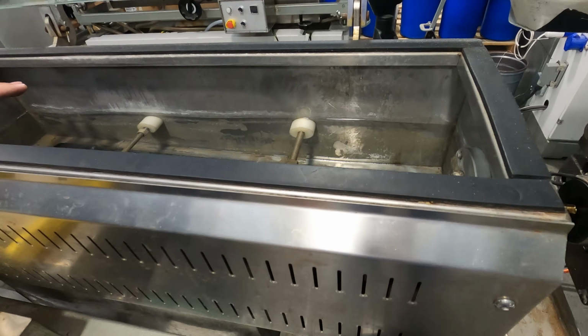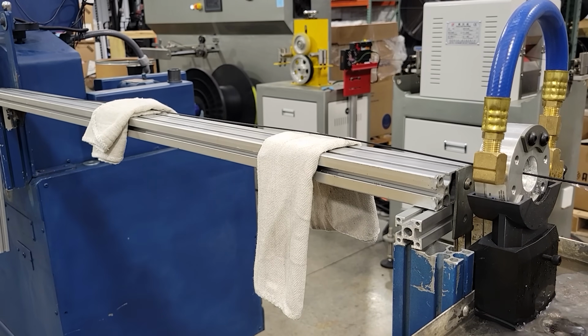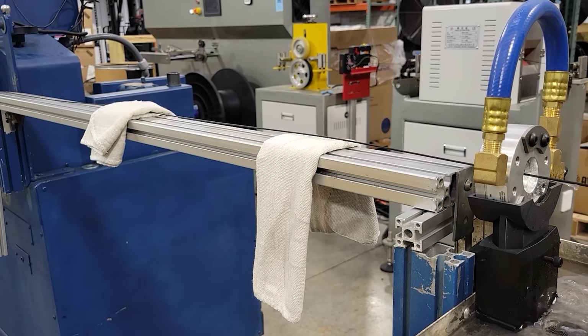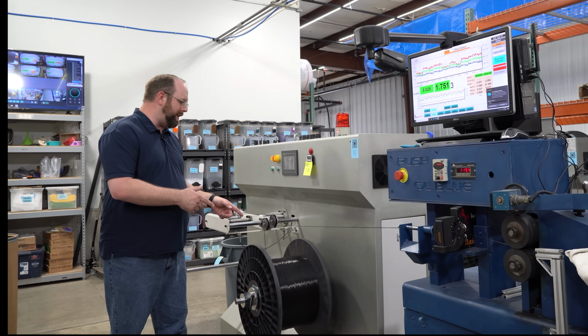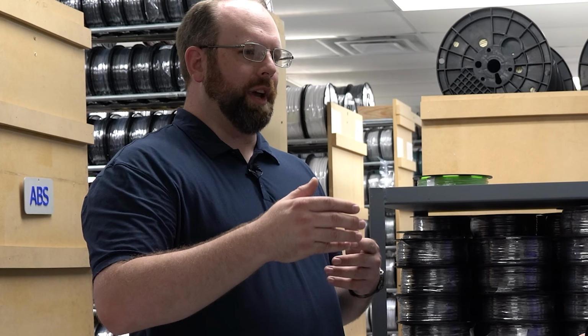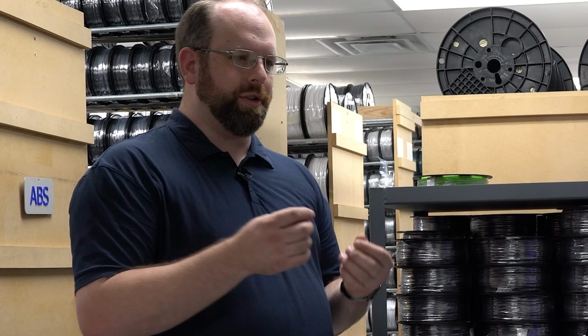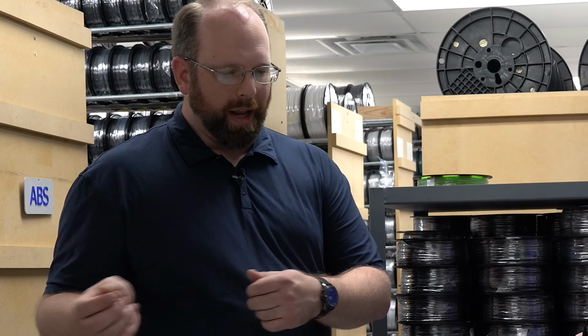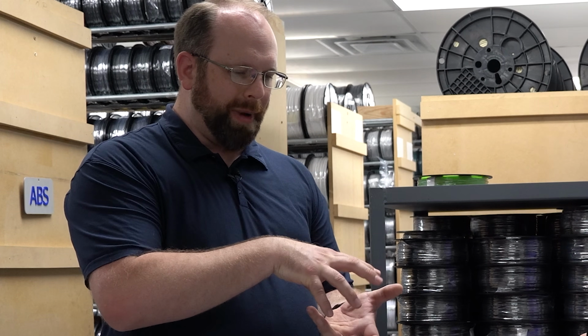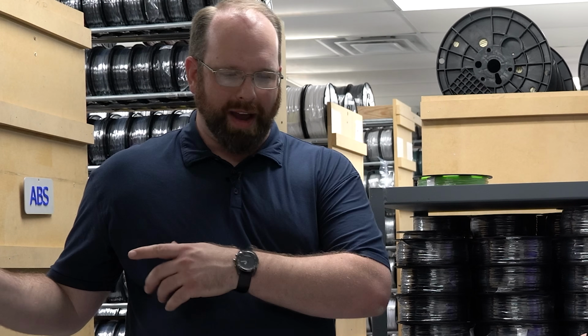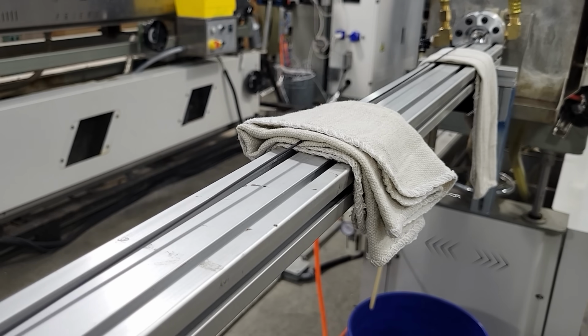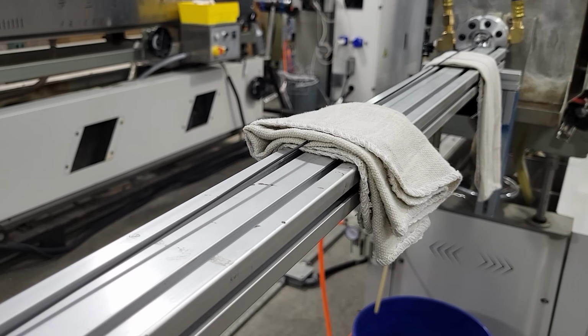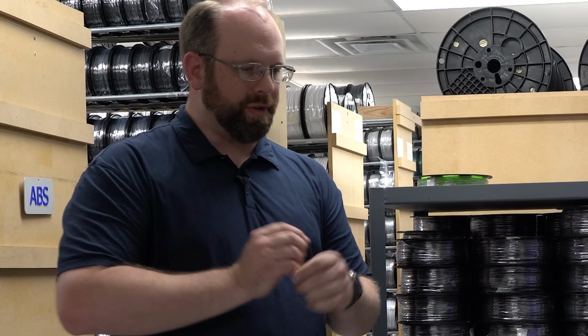I remember you had mentioned when we were talking off camera that, for example, your material comes off the line, it goes to the water tank, and it gets air blasted. But some other manufacturers don't do that. Yeah. So sometimes that's one of the benefits of our process going onto the bulk spool: you do get perhaps some residual moisture depending on the facility and the manufacturer. And when they wind directly off the line, they can actually trap moisture inside that vac seal pack with that desiccant. They'll have it come right out of the water tank. They'll probably have an air blow off. They might even have rags like we have, but there could still be a little bit of residual moisture on the surface of that, and it goes straight onto the end spool.